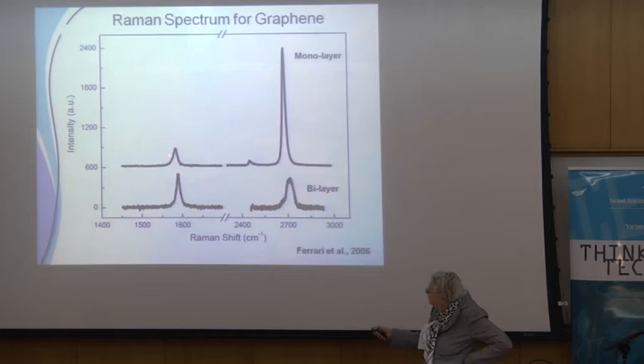Intensity is very small. Second order term, intensity is huge. So what's going on here? This material is linear E versus K. When you do spectroscopy, the intensity of spectra goes up if you're in resonance with the laser energy. It turns out with graphene, you can be in resonance not only for the initial state, but with all of the intermediate states.